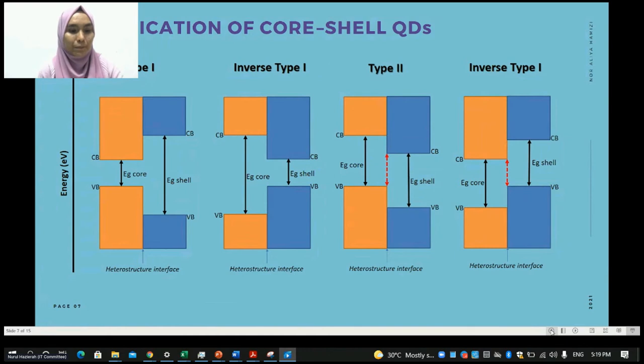sulfide shell. In reverse type 1 configuration, the core has a wider band gap than the shell, and the conduction and valence bands of the shell lie within those of the core. The lowest available exciton energy separation occurs when the charge carriers are localized within the shell. Changing the shell thickness will enable us to tune the emission wavelength, whereas in type 2 configuration, the